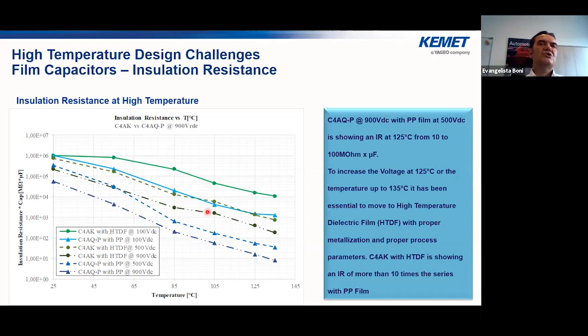The dark green line shows the insulation resistance of a new film called high temperature dielectric film, HTDF, that is showing more than 10 times the insulation resistance with respect to the standard polypropylene film. This is a great achievement, and it permitted power box capacitors to work at 125 degrees at higher voltages, and also to work up to 135 degrees. Otherwise, with the standard polypropylene, it was not possible.